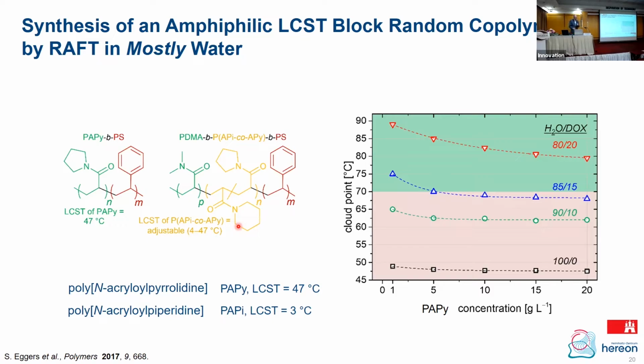Here, I just want to stress another point. The LCST, even the highest LCST we have here with 47 degrees, is still too low to carry out the thermally initiated RAFT polymerization. So when we want to polymerize such a monomer in water, the polymer will precipitate, and we go to a higher temperature. That's why Stefan said, okay, I can't do the green chemistry, I can't do it just in water. However, I can also avoid using too much organic solvent. So he added a little bit of dioxane.